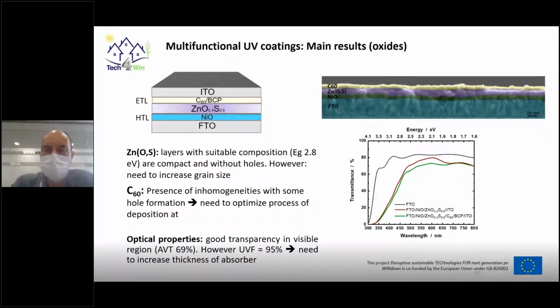These are the results obtained at solar cell level for the oxide-based strategy. On the top left-hand side, you can see the device architecture that we have developed. We are working with an oxysulfide absorber layer. These layers are synthesized by reactive sputtering, and we have demonstrated the possibility to control very well the sulfur to oxygen relative ratio. We can switch from ratios of 30% sulfur up to 90%. So we cover a very wide range of band gap values and compositions. The layer in this device corresponds to a 60% sulfur content, which leads to a 2.8 electron volts band gap.